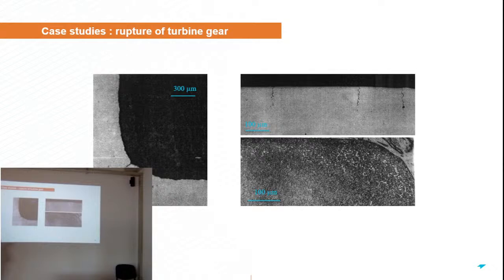To get a hard surface in that part, we enrich the surface of the steel with carbon, because it's cementation, okay, case cementation. And you can see here that the cementation was not properly conducted. As you can see, the iron carbides produced by the enrichment of the surface with carbon are poorly disconnected from each other. So, in other words, the carbide particles are connected to each other, which makes a preferential path for the fracture to propagate. Okay, so this was the reason for this failure, the poor surface treatment produced on this material.